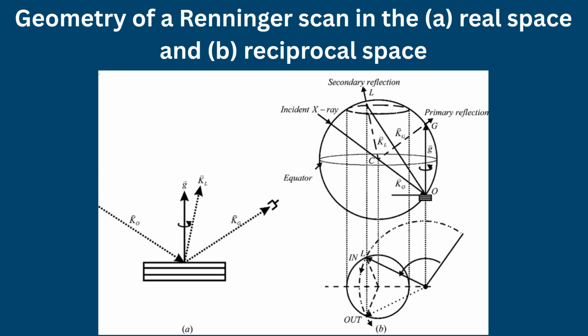More advanced analyses involve reconstruction of the crystal structure from diffraction intensities. Symmetry elements, lattice constants, and atomic positions can be determined with remarkable precision. Techniques such as Renninger scans and reciprocal space analysis enable detection of forbidden reflections and subtle structural distortions that are critical for identifying polymorphs and isomeric structures.